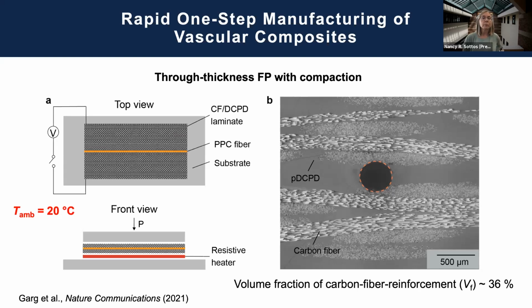Looks good. You notice the example I'm showing here is a fairly low volume fraction fiber reinforcement. That goes back to this notion: as I add more fibers, I lose heat. But in the end, we're able to reduce this cure time down to roughly 30 seconds from almost a 2-day process from before. It's 10,000 times less energy and 1,000 times faster.